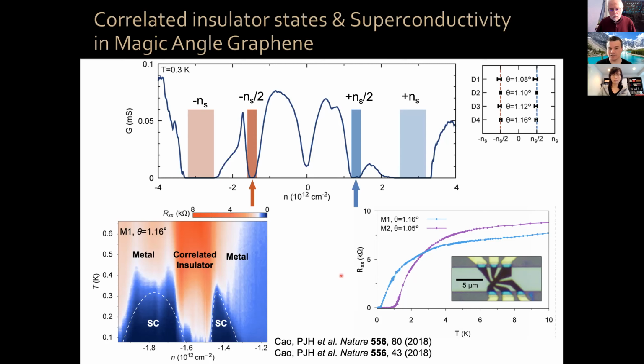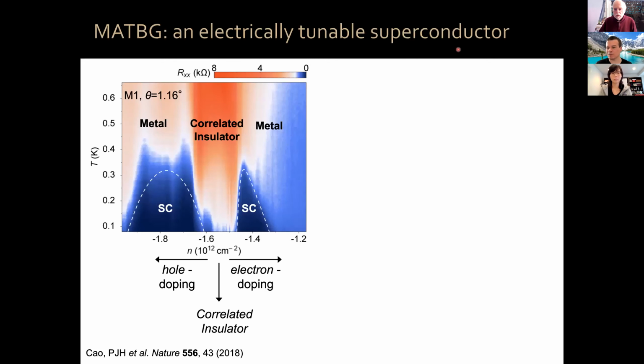the fact that, if you dope away a little bit from these correlated insulator states, your system becomes a superconductor. Magic angle twisted bilayer graphene becomes a superconductor, okay? And not just any superconductor, okay? It is an electrically tunable superconductor, okay?